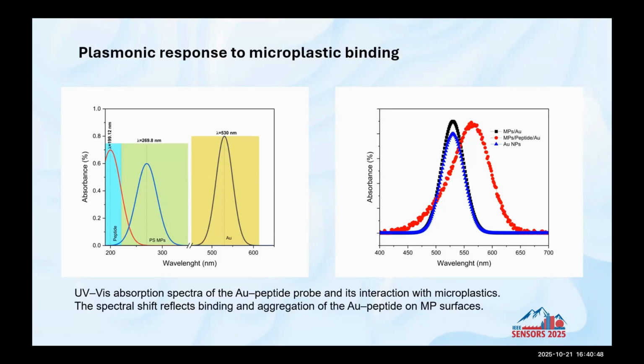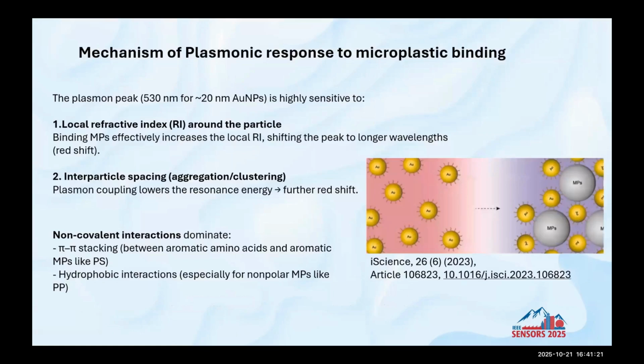So it means that there is no random affinity between the gold and microplastic. But when we add the peptides, the gold has a cysteine, which has an affinity to bind to one head of the peptide, and the other end of the peptide bonds to the microplastic. All this combination and aggregation shift the wavelength, because it changes the color to a reddish color, which goes to the higher wavelength of the absorption. So that's the way we could detect it through the spectroscopy-based technique, both visually as a yes or no, or quantifiably through this spectrum measurement.